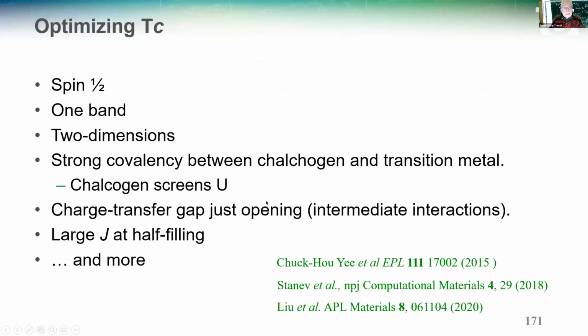So to summarize and conclude, optimizing TC means, in this case, spin 1/2, one band, two dimensions. Two dimensions favor strong covalency. And I suppose one should look at other chalcogen and transition metals that could have a strong covalent bond. You have to be where the charge transfer gap is just opening, with an intermediate interaction, and a large value of J at half filling, and more.